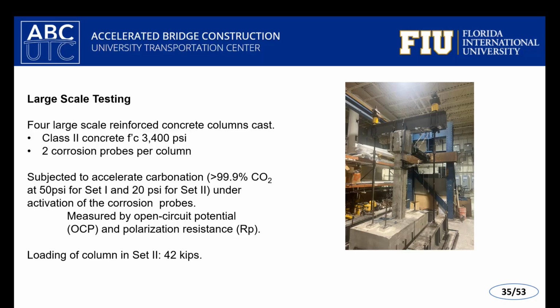And so we subjected those columns to accelerated carbonation. We had a greater than 99.9% pure CO2. We pressurized a vessel to around 50 psi for one set, and 20 psi, a little bit slower, for another one, to try to force that corrosion to measure the development of corrosion.